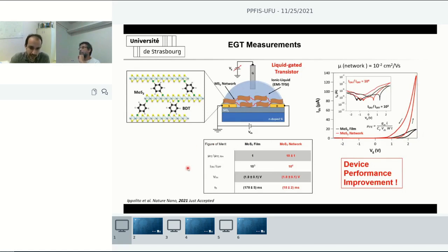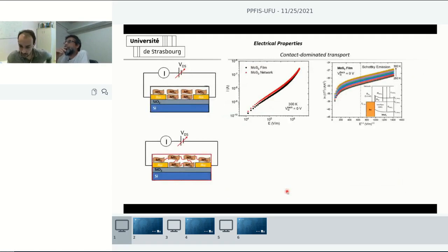If we calculate important figures of merit for films and networks, we see that the field effect mobility increases by a factor of one order of magnitude. The on-off ratio also increases by 1 order of magnitude. The threshold voltage remains nearly the same, meaning that there is no doping, no charge transfer from molecules to the material, to the molybdenum disulfide. And the switching is faster for our devices employing networks.